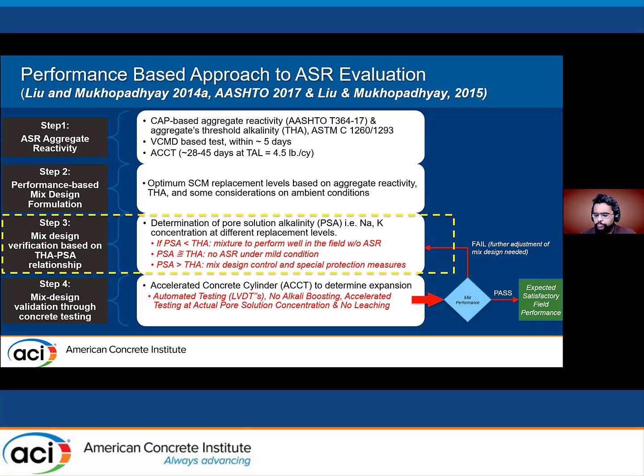Once an optimum level of SCM has been determined at this stage, we finally go to the mix design verification, where the ACCT test is performed for the desired optimum SCM replacement level. This is performed with no alkali boosting, so at the actual pore solution alkalinity, to determine the true performance. And it is the third step which would be the aspect of the further discussions.